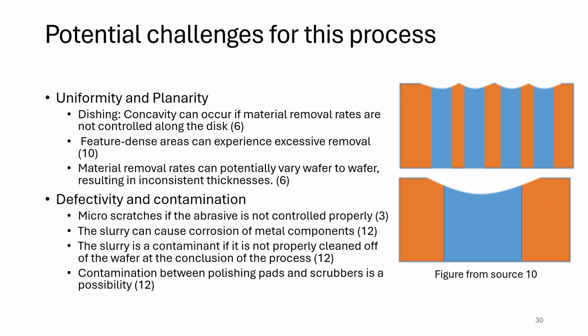Common defects we can encounter are scratches, residues, corrosion and pitting, dishing and erosion, and particles left behind on the surface. Mitigations can include using the correct abrasive size, proper inhibitor balance, proper pad conditioning, using an optimized rinse process, and a robust post-CMP cleaning process.